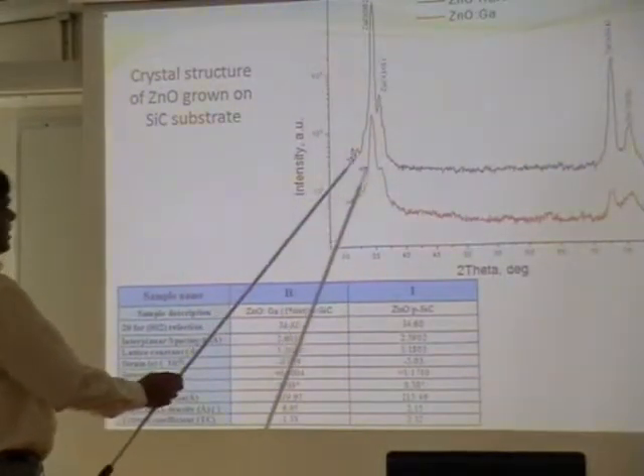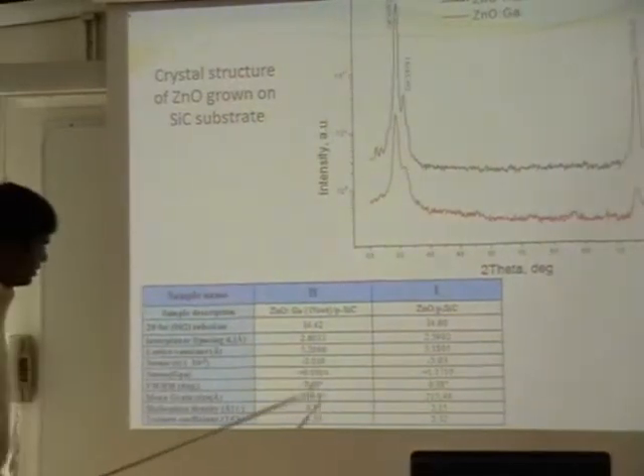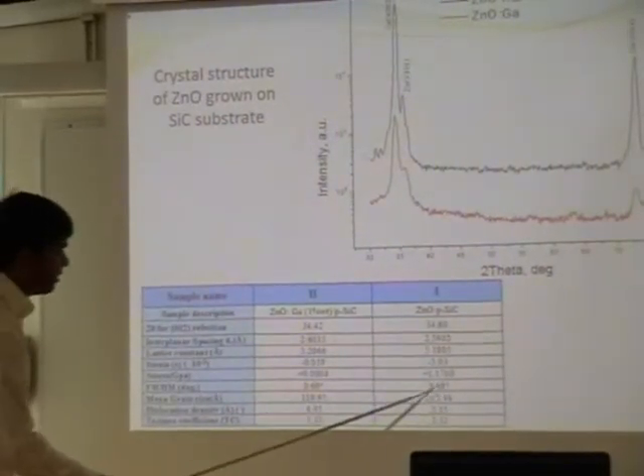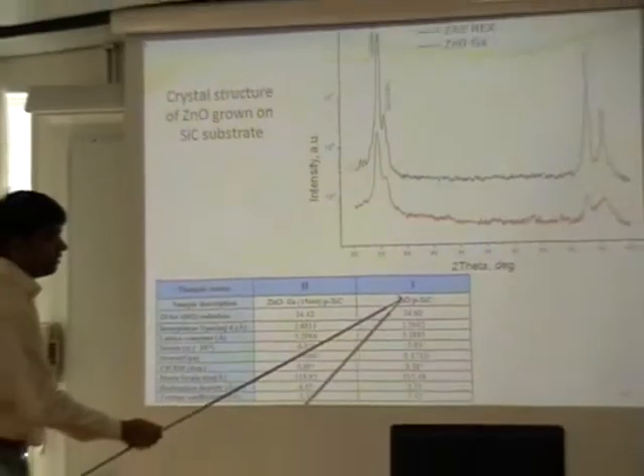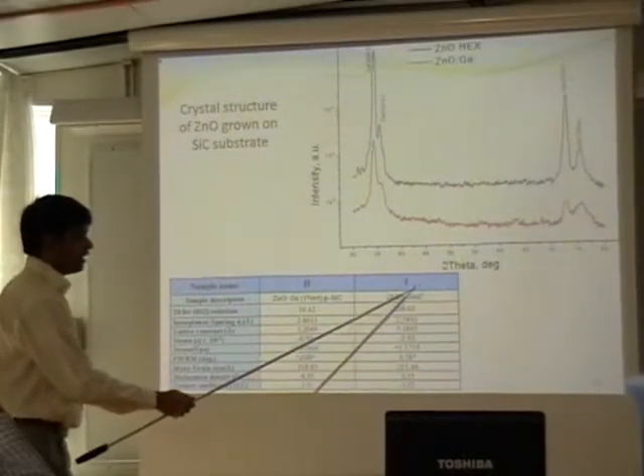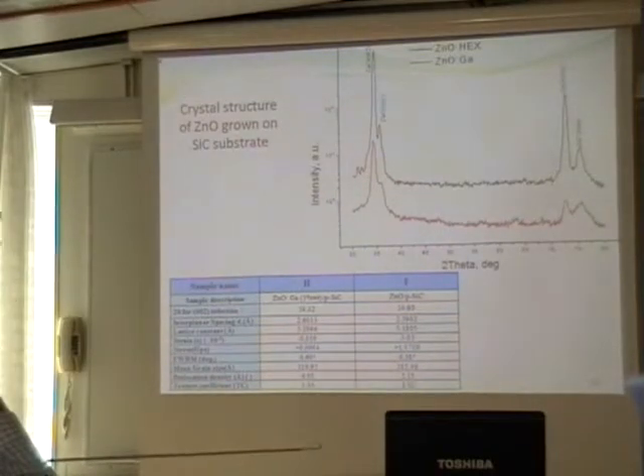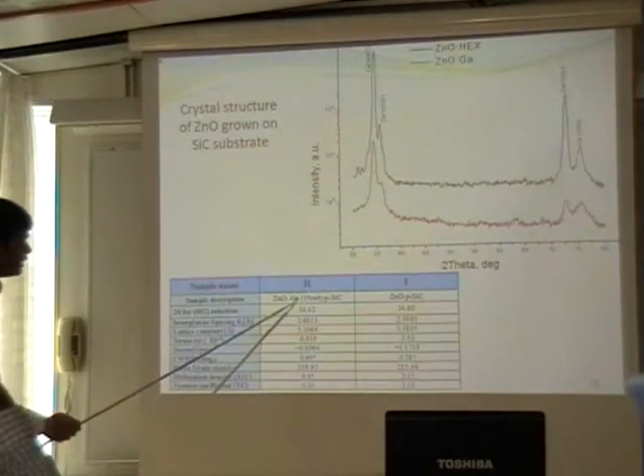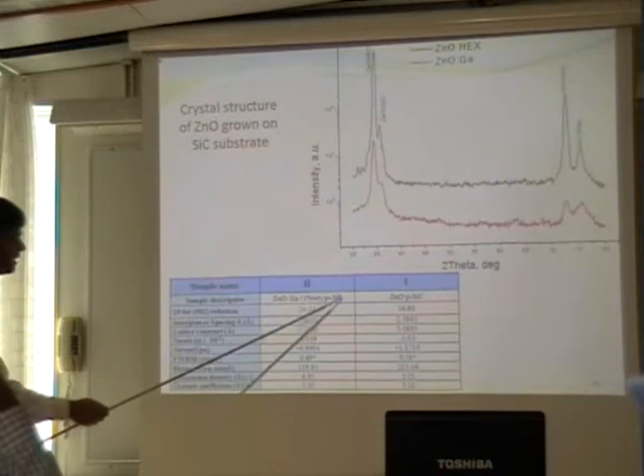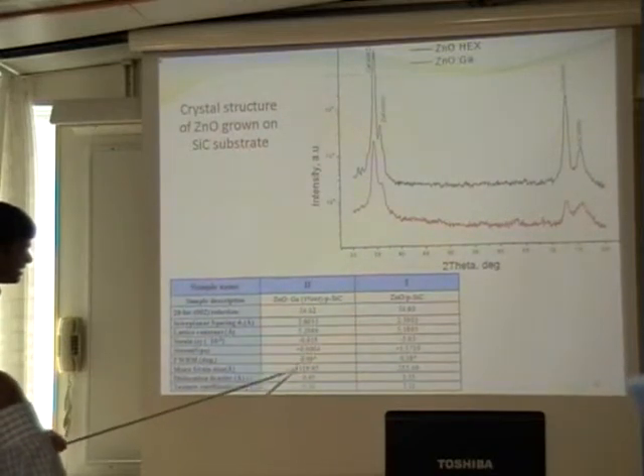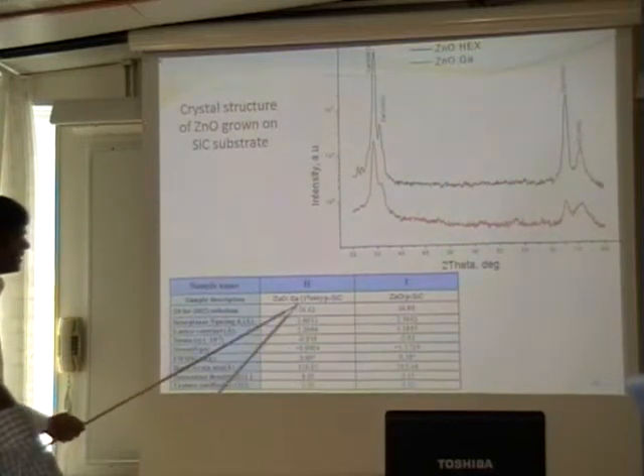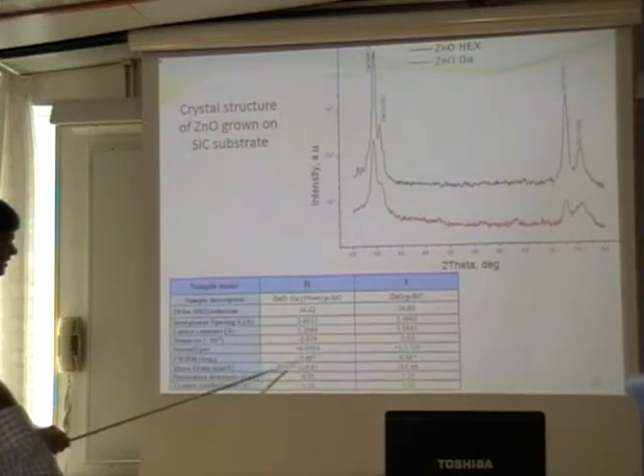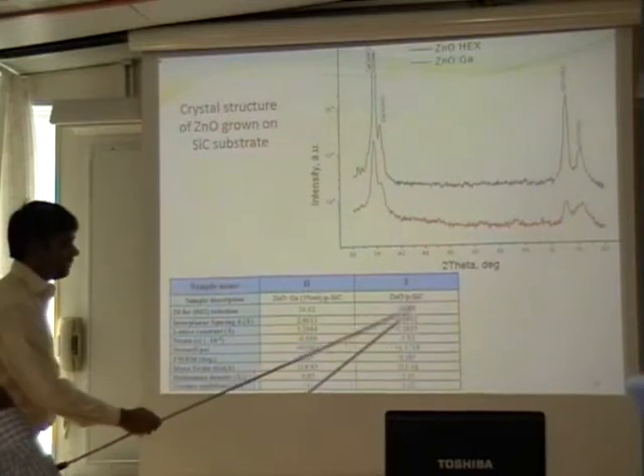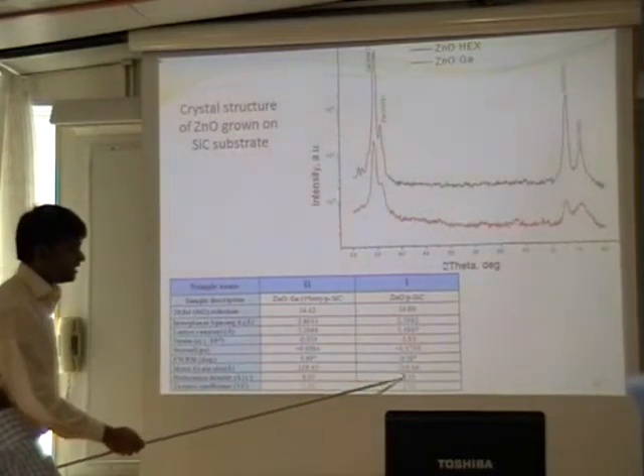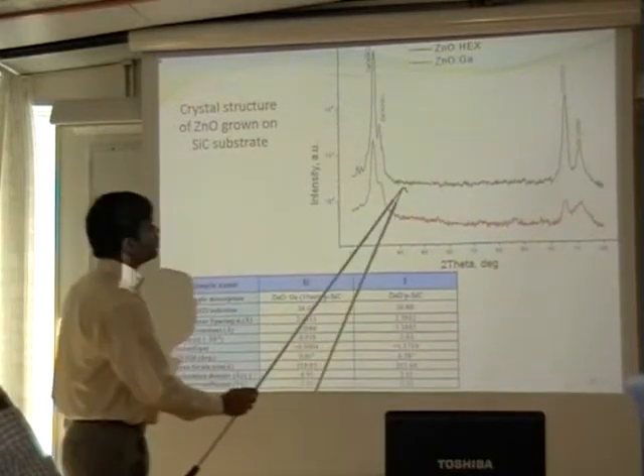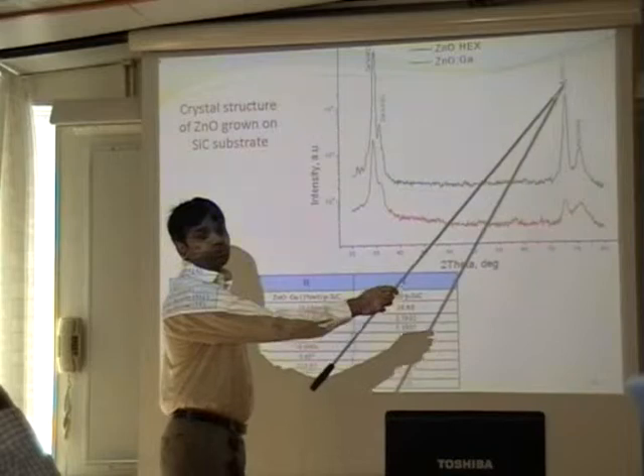Through structural property, they show the grain size increased, which the zinc oxide was grown on a p-type silicon carbide, and the zinc oxide doped with gallium 1% on a p-type silicon carbide, grain size decreased. Maybe some effect of gallium on it, but in the p-type the grain size, and here no other peaks were observed